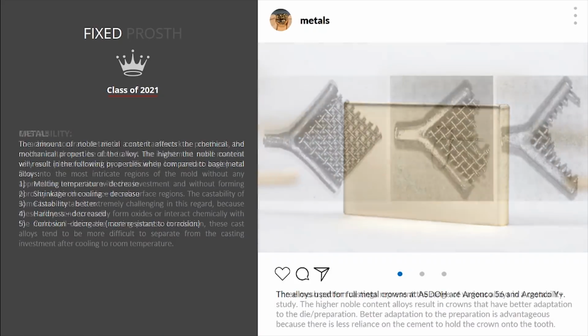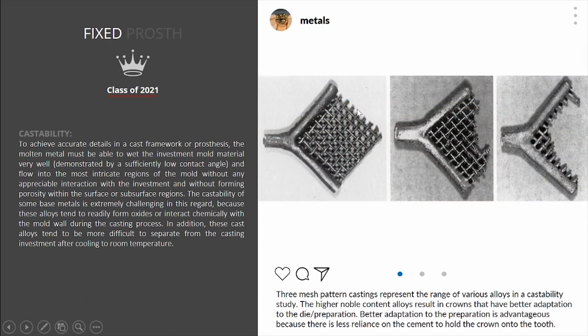So let's talk about castability here. This is just a diagram showing how they measure castability. They made a wax pattern of sort of this mesh, and then they were trying to determine which metal can fill in and really cast all the little detailed structures of this mesh pattern. And what we find out is that the gold or the noble metals, noble alloys, tend to have better castability and are able to fill in with detail this whole mesh network here, or this whole mesh casting here.